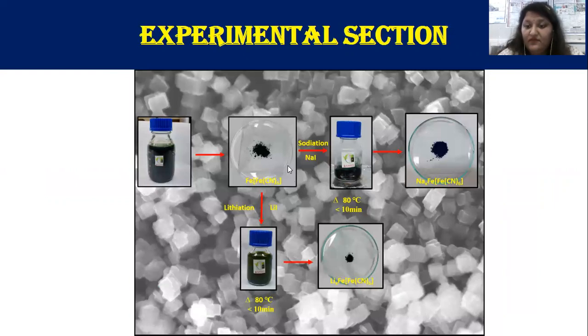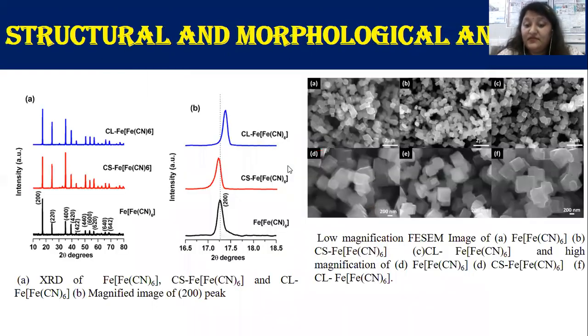So our experimental part mainly deals with the preparation of FeFe(CN)6, which has been obtained using a iron ion source and K3Fe(CN)6, and subsequently this FeFe(CN)6 was taken for chemical reduction to form sodiated Prussian blue analog, NaxFeFe(CN)6, which is named CS-FeFe(CN)6, where CS indicates chemically sodiated, obtained by using NaI, sodium iodide, as a reducing agent in a solvent medium at 80 degrees Celsius for a period of less than 10 minutes at ambient atmospheric condition. Similarly, lithiated Prussian blue analog was also obtained by adding lithium iodide in place of sodium iodide to obtain LixFeFe(CN)6.